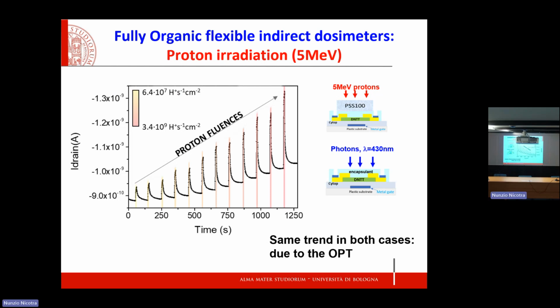Now, what is interesting to conclude is that understanding what is going on and what is the final readout that we get is not always trivial. You always have to go back to the physics. Why? Because that is what you get under increasing proton fluences. This is the current and this is the time. What you see is that indeed, by increasing the proton fluence, the signal increases, scales linearly, but also there is what could seem like a baseline shift.